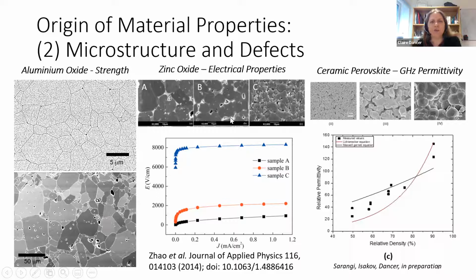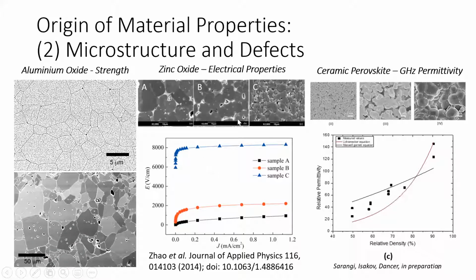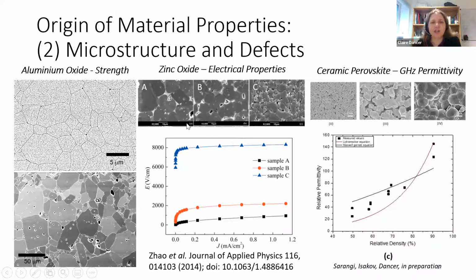The second example of where microstructure can affect properties is this one I've taken out of a paper by Zhao on zinc oxide. So zinc oxide, really nice electrical material. And in this case, they've made zinc oxide by a few different methods. It's got an additive in, it's got some bismuth oxide and things in it. But they've basically made 3 materials with different microstructures. So similar, basically the same chemistry, but with different microstructures.